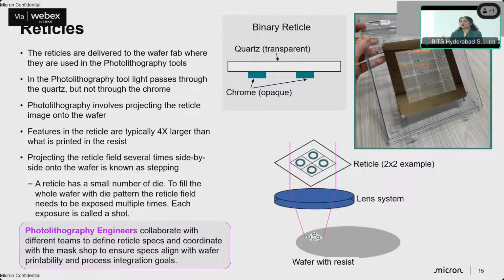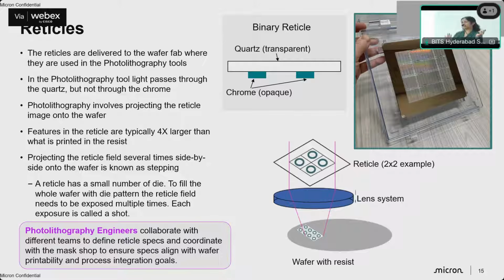Now, the reticles. The way we visualize reticles, they are like stencils actually, right? With certain open areas where you create a design with certain features, everything else remains the same. The way reticles are created, the design is 4 times the size of what you are going to print on the wafer. The scanner tools that we use take care of the shrinkage by a quarter. Each reticle will have a certain field, and as I mentioned, a collection of die are placed in each field so that they cover maximum area, and you go step by step to scan it on your wafer. So that's our reticle to photo process.